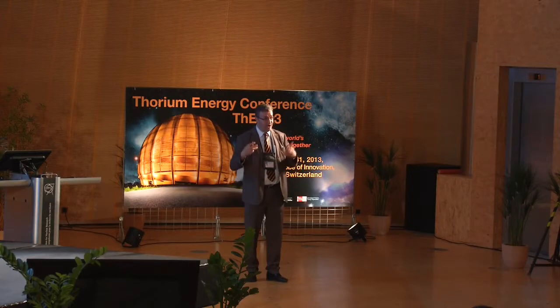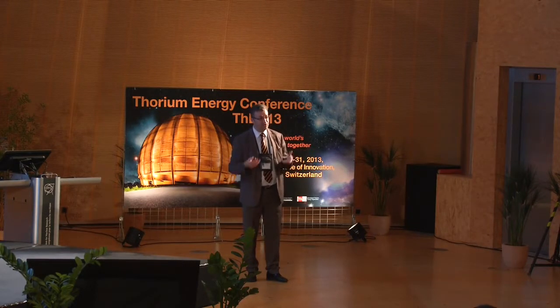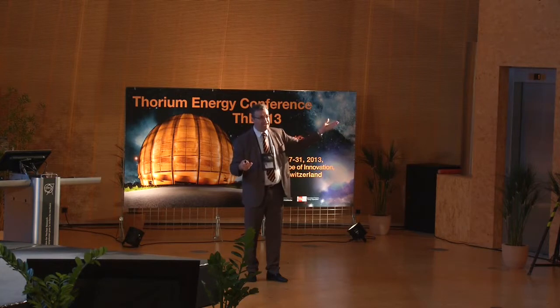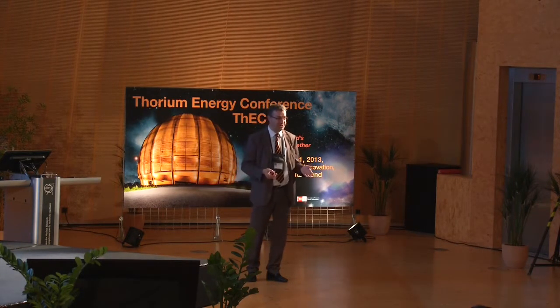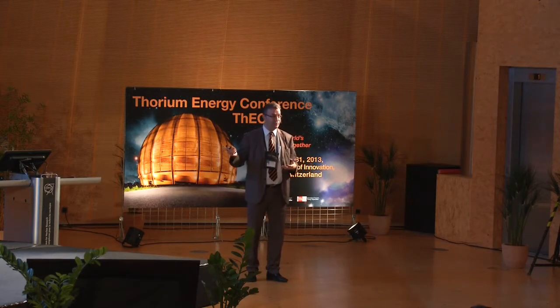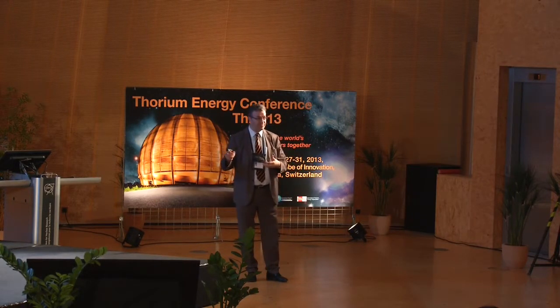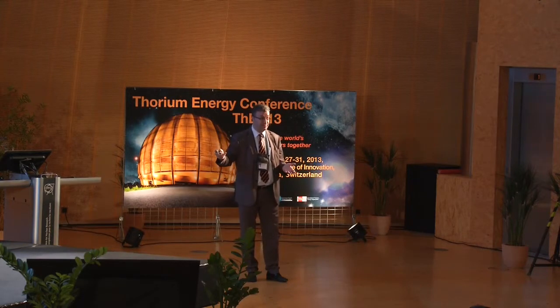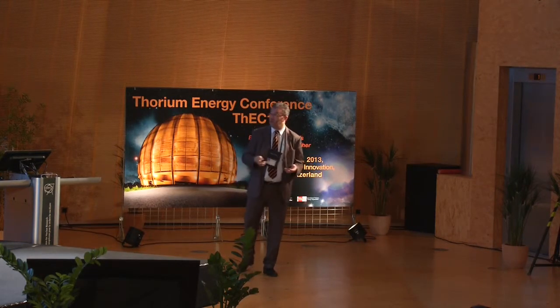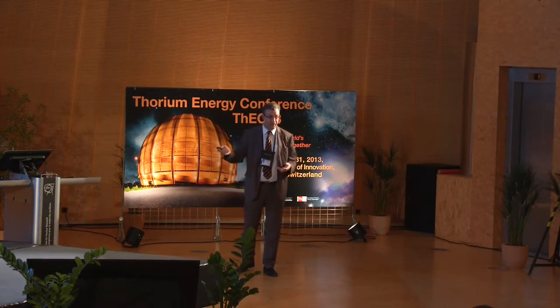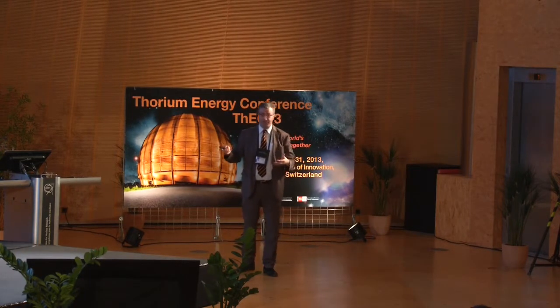But should I wait until I make those new materials that will allow me to work at higher temperature? Those materials do not exist off the shelf today. So I think we can afford for a research machine to make it with lead bismuth, but without forgetting that the final objective is to go to pure lead, and so develop the needed materials that can sustain higher temperature. But here we have gone lead bismuth because of this constraint, and the corrosion is less, I would say, problematic at those low temperatures.